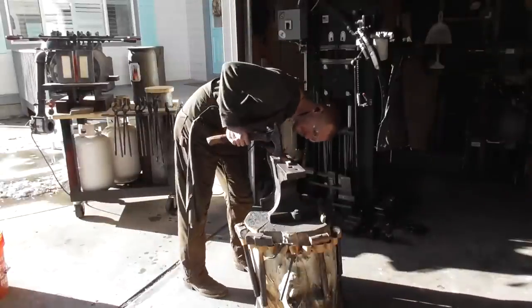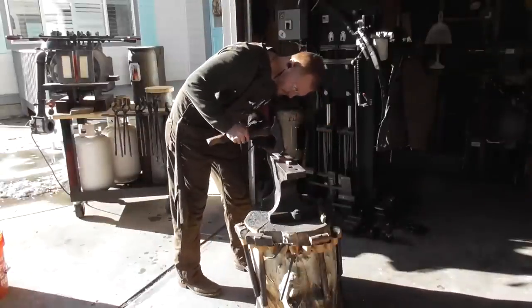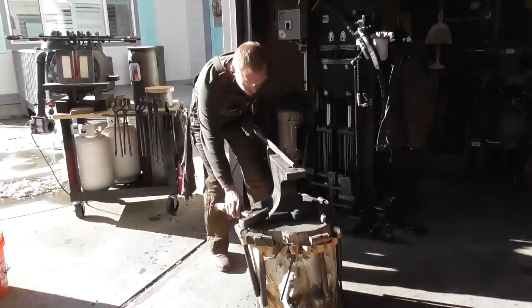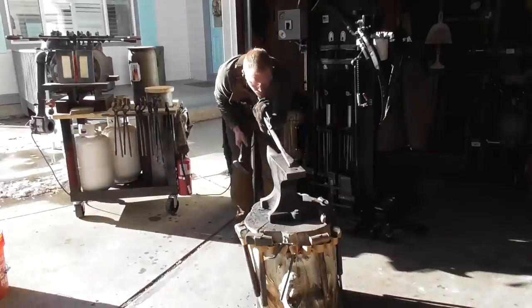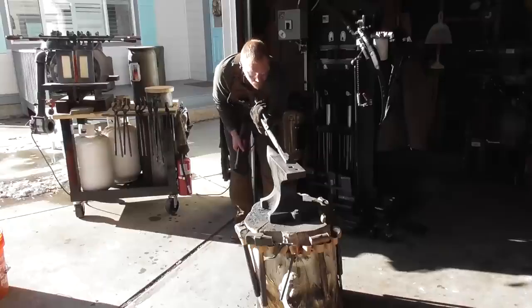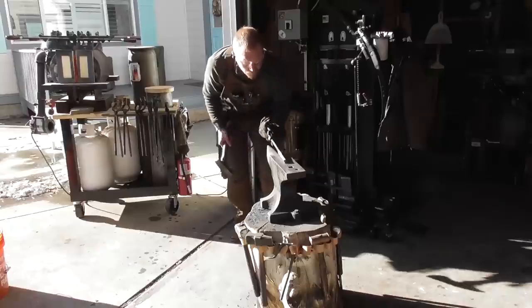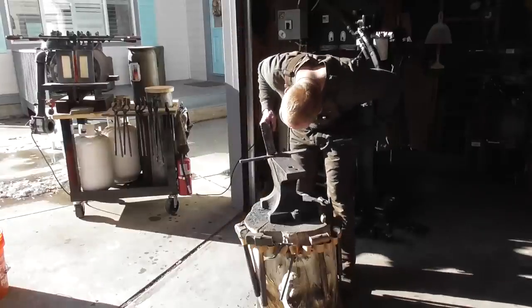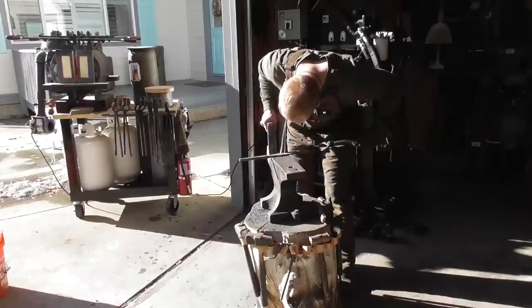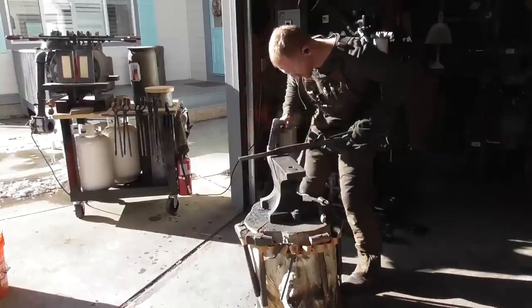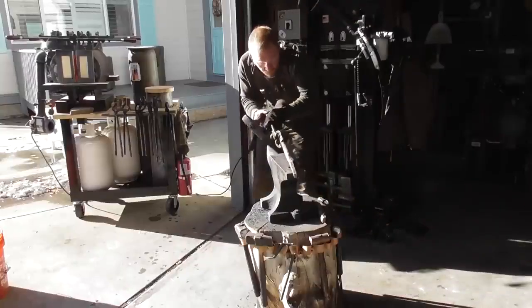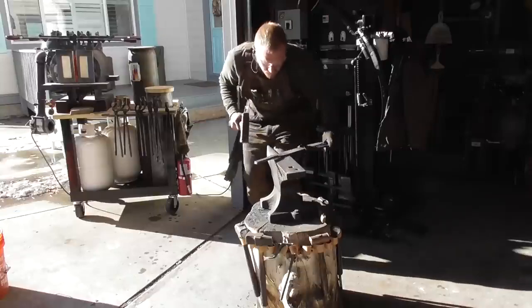I'll also do some very light taps with my hammer at a low temperature, just to get everything perfectly in line. You don't want to, in the end, be starting to grind on the blade and then realize that there's a warp or a bend that's so bad that you're going to have to go back into the forge in order to straighten it.